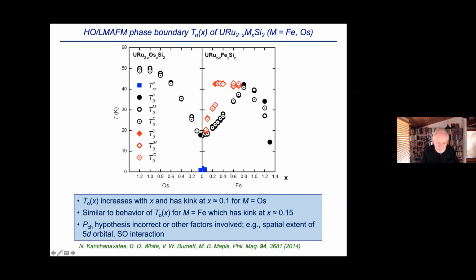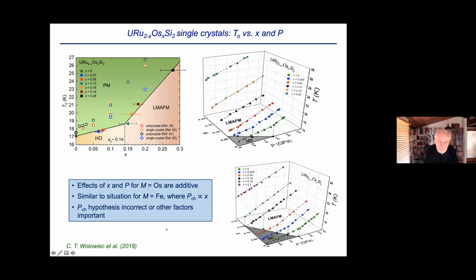So since you could associate it with a negative chemical pressure, this indicates something else must be going on. One thing would be a larger spatial extent of the 5d orbital for osmium, or an increase of the spin-orbit interaction. And indeed, both of those contributions could account for this behavior, and the actual chemical pressure is really a minor contribution that's dominated by these other factors. So here's some high pressure data for osmium substitution, similar to what I showed you before.